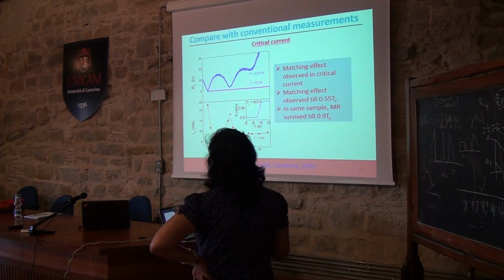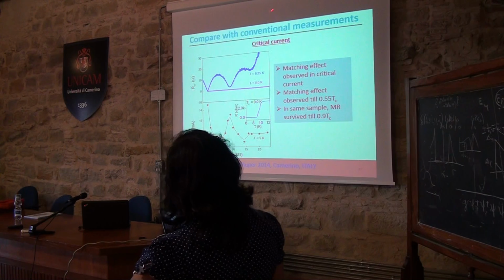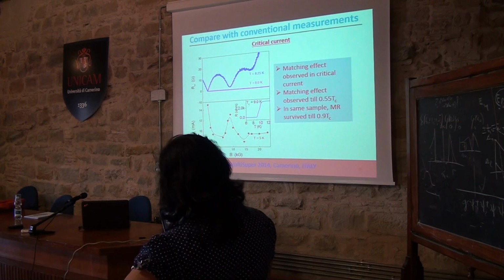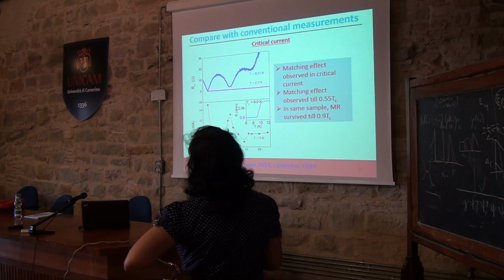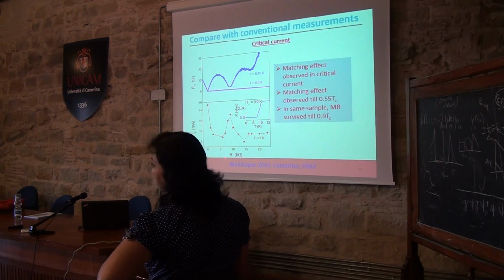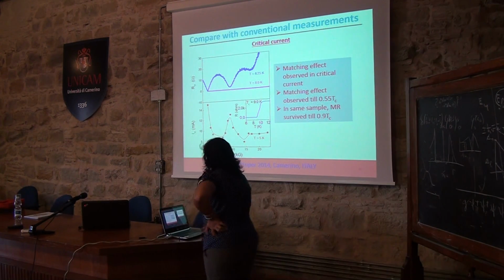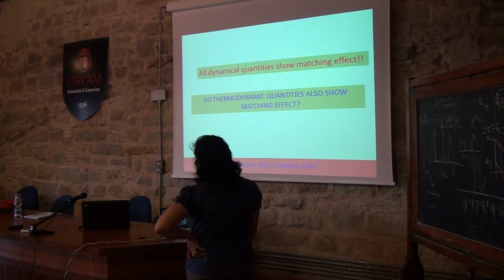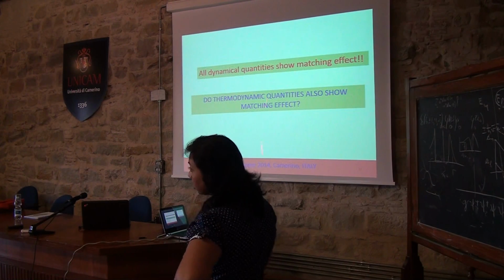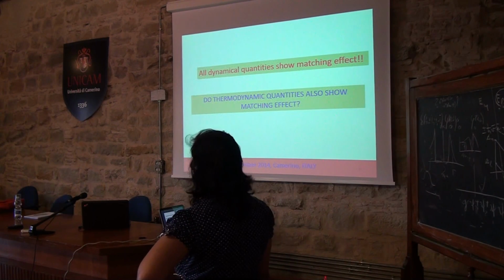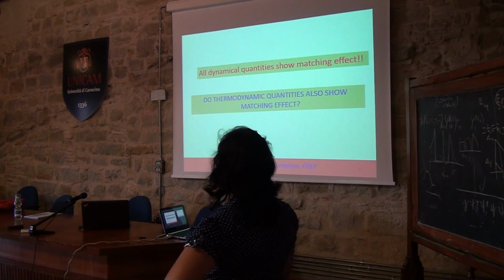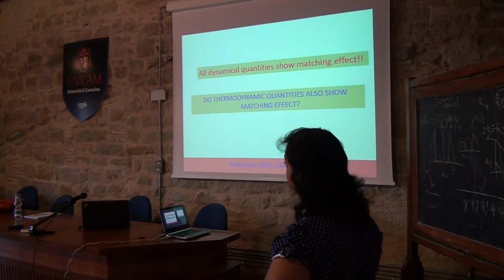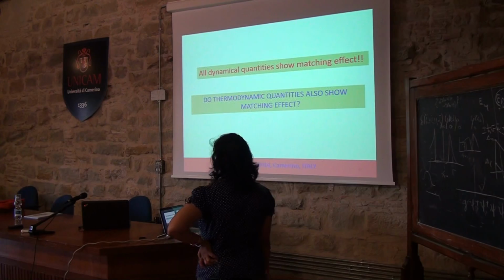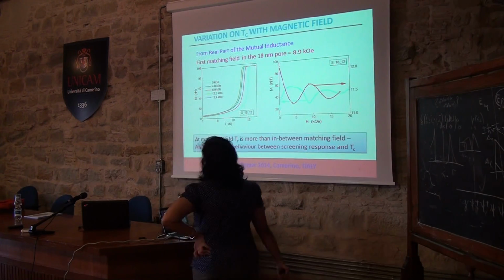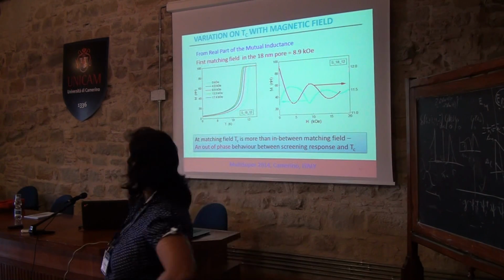We also measured the critical current of these systems, and we saw these oscillations. So the critical current gets enhanced at the matching fields. So till now what we have seen is that all dynamical quantities show this matching effect. And we wanted to ask ourselves whether thermodynamic quantities also show this matching effect. For that, we wanted to look at the transition temperature.